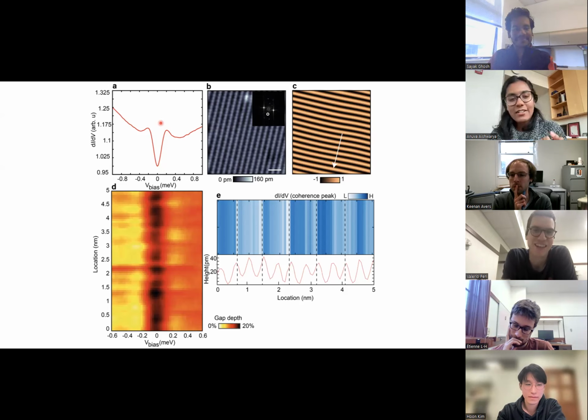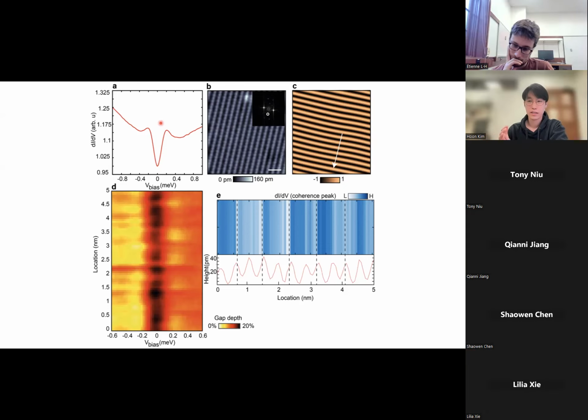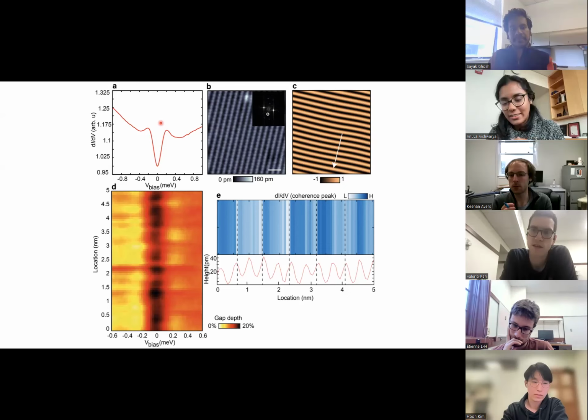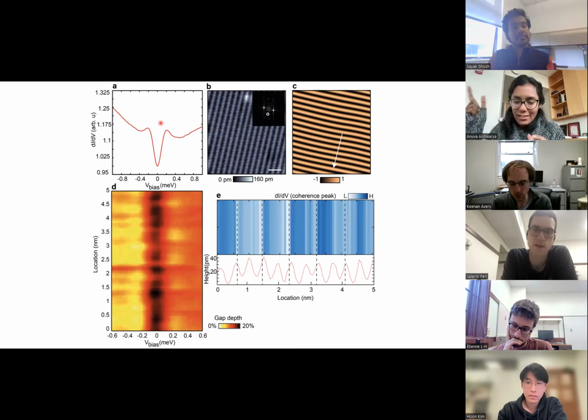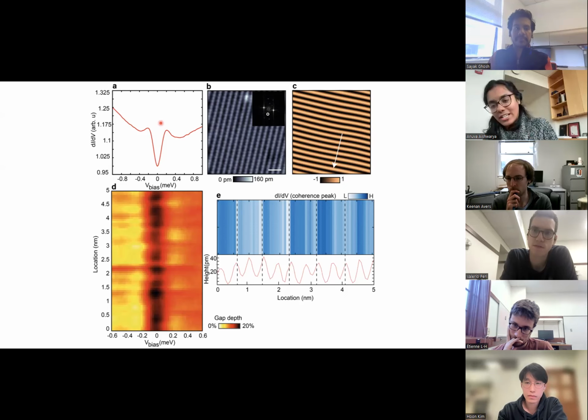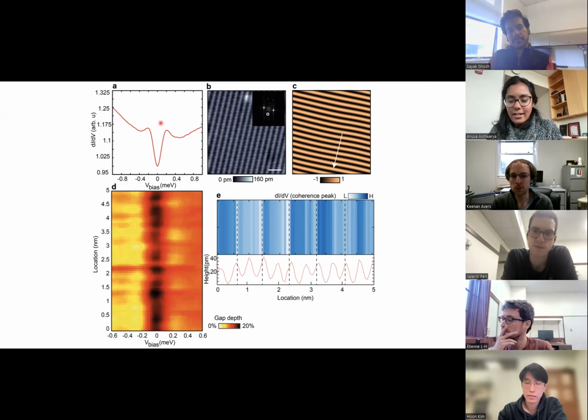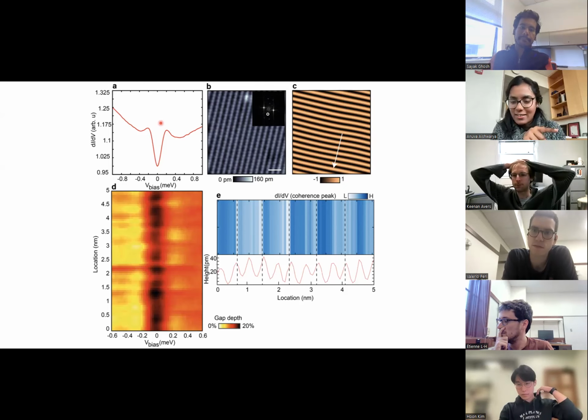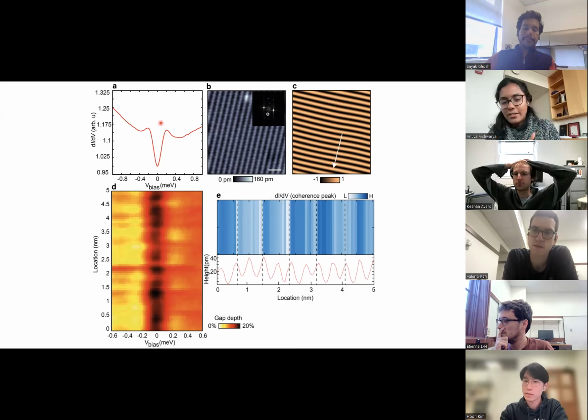Remember that if you have the magnetic field exactly perpendicular, the HC2 is pretty high to reach with our STM. If we have a tilted sample, only then we can reach the HC2, and then it goes away. So if you ask whether mirror symmetry breaks, if you apply a perpendicular magnetic field at 1.7, it doesn't.